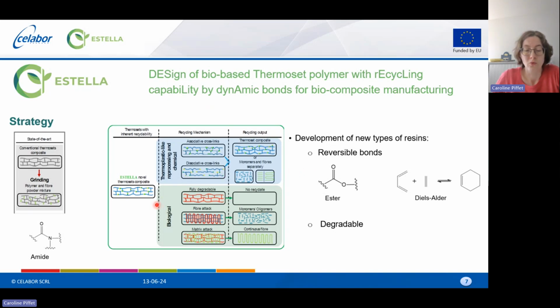The other option is to degrade the new resin that is studied. And we study in the ESTELLA project the biological degradation by microorganisms with different mechanisms. The first is the fully degradable composite. In that case, you don't recycle the resin or the fibers. You have no waste at the end. The other option is to attack the fibers and collect the monomers, and so to obtain the new precursors that can be reused again. And the third possibility is to degrade the resin and keep the fibers, and those fibers can be reused in new thermosets.